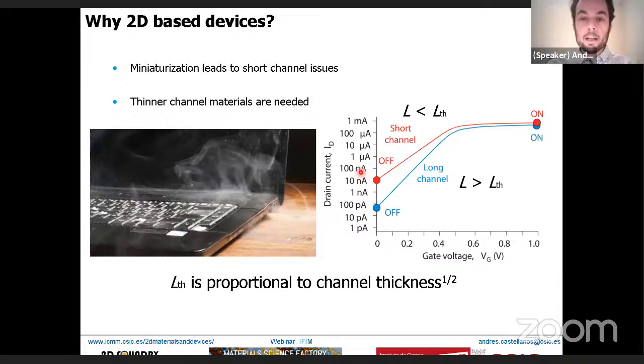All the microprocessors in electronics, if we don't reduce this off current, won't work because of overheating. This is where two-dimensional materials enter this equation of beyond CMOS: the threshold length is proportional to the square root of the thickness of the channel. Therefore you want a semiconductor channel as thin as possible, and there's nothing thinner than a single layer two-dimensional semiconductor material. So you can push the limits of electronics a bit more than with silicon if we move to two-dimensional materials, and that will happen eventually.